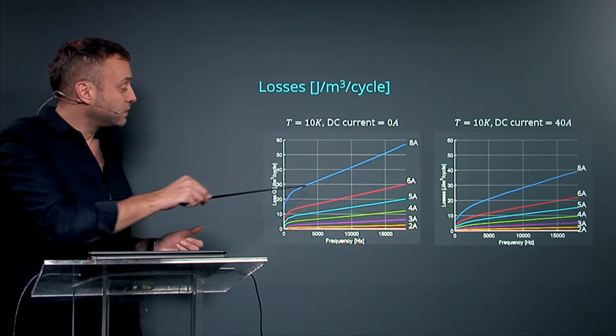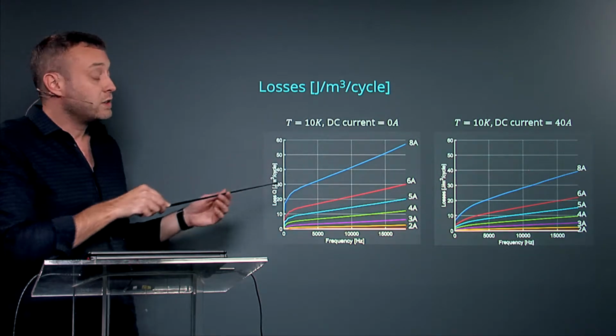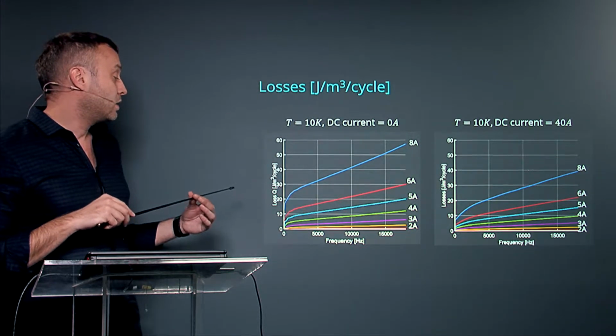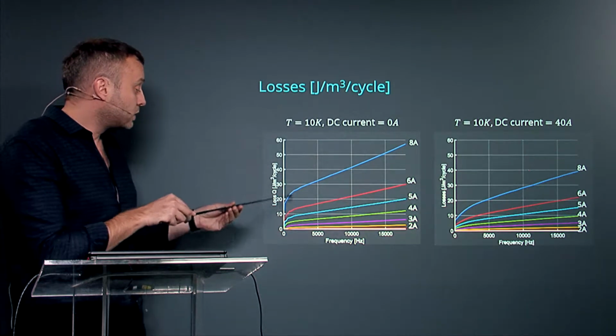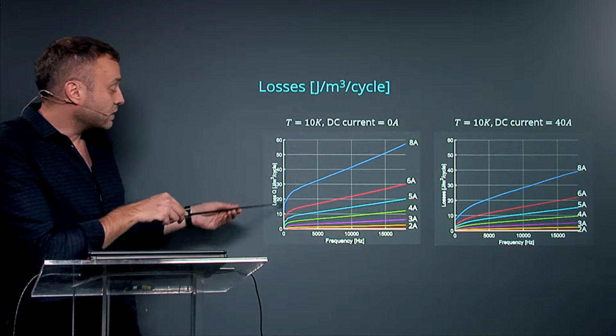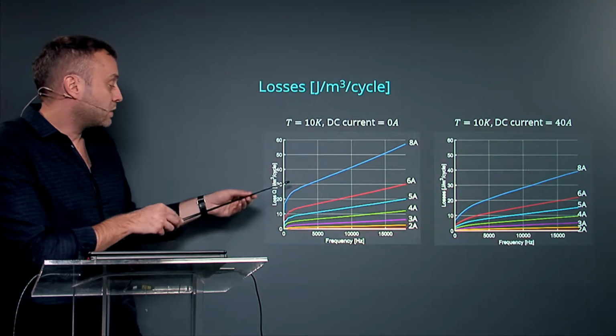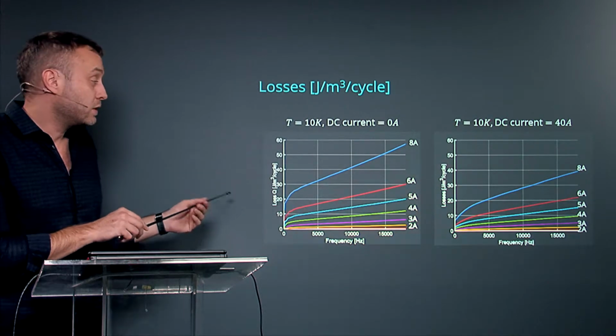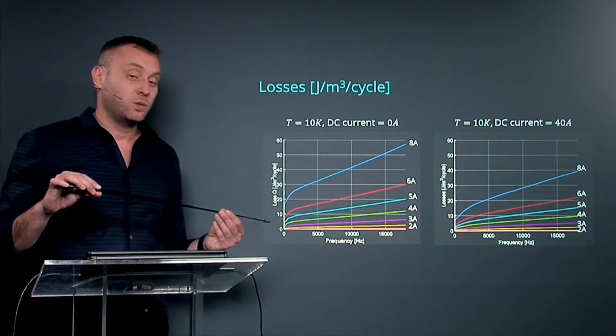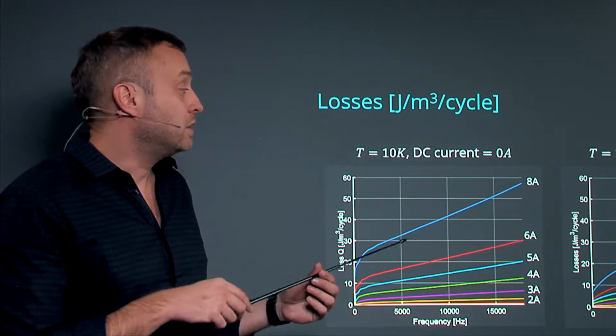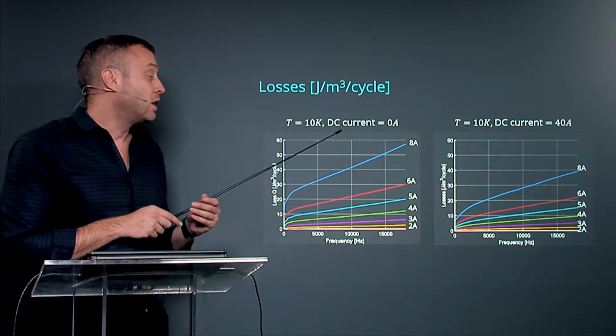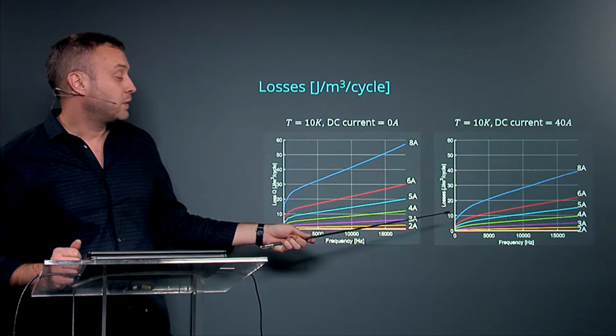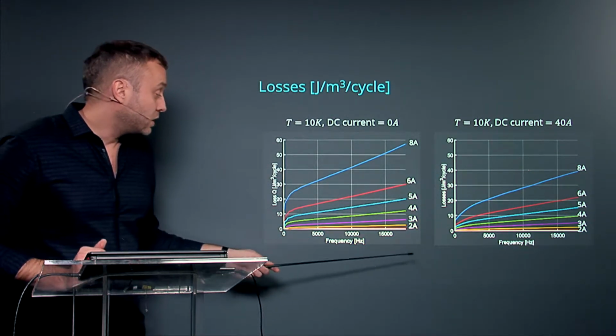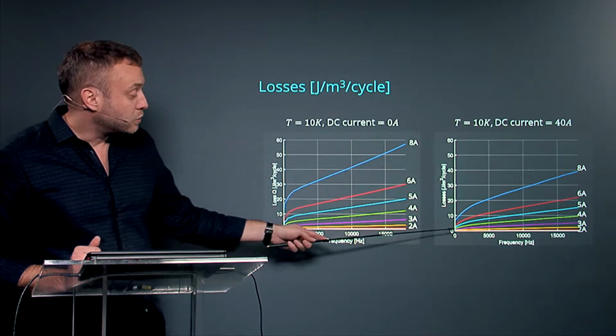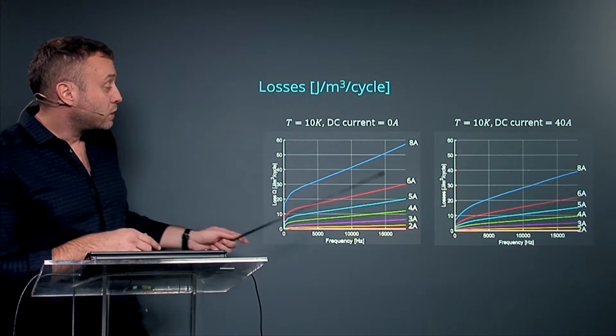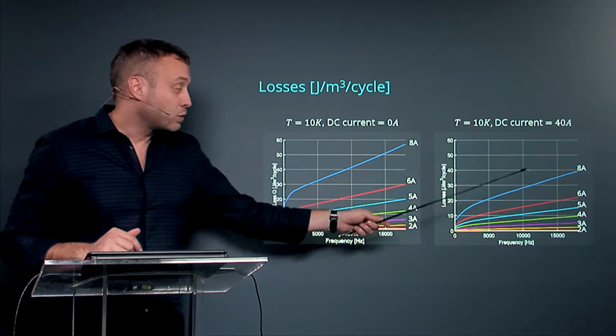In this area, the energy loss is very linear as a function of frequency. But for lower frequencies, the dependency is different. There is some different curvature of it. And surprisingly, when we add a DC current of 40 amperes, the overall energy loss is reduced. And this low frequency area also changed its shape. However, the overall dependency on frequency is the same.